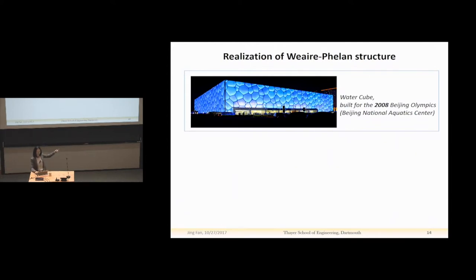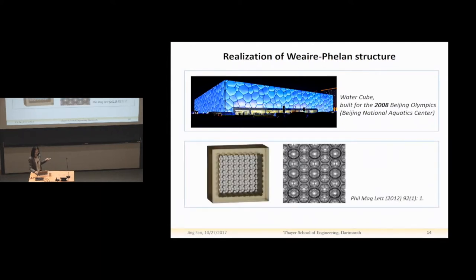Actually, the first realization in an experimental system in the lab was conducted in 2012, when people used a 3D printed chamber like this. It's like a box with an open opening. All 5 surfaces of this box have exactly the same structure as the Weaire-Phelan structure, and this rough surface served as a guide to guide the packing of bubbles in this chamber. So for the first time, people realized the Weaire-Phelan structure in a foam system.